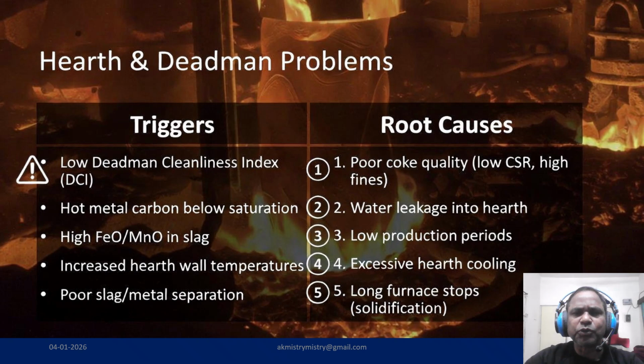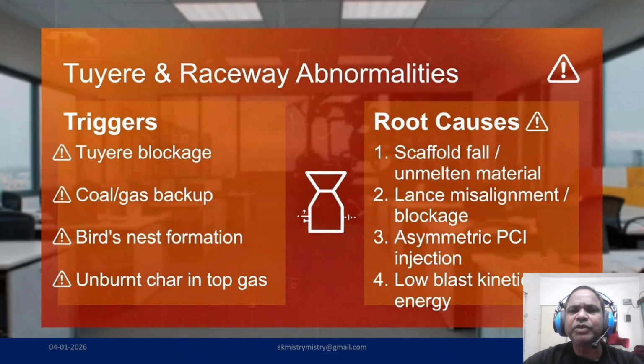Now, moving to the combustion zone, we monitor tuyere and other raceway abnormalities in many cases. Signs of trouble include tuyere blockages, coal or gas backups, and formation of a bird nest of unburned material. The root cause frequently involves a scaffold fall or unmolten material dropping from the raceway, or many times we come across an unprepared burden descending down or peeling off. Additionally, lance misalignment or low blast kinetic energy can prevent the pulverized coal from burning efficiently, also leading to unburned char in the top gas.